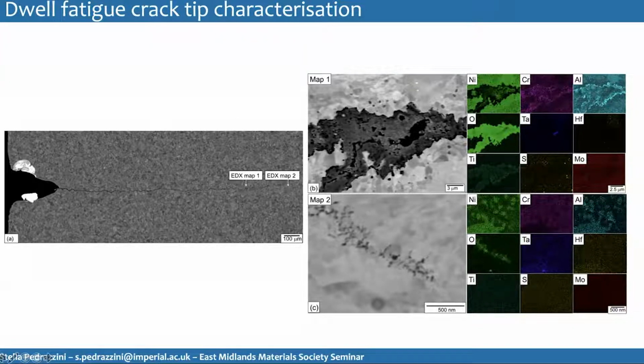At the very edge of it, what I got is alumina. Actually, there's no evidence of sulfides forming. So this looks like the crack initially propagates through a mechanism of formation of chromium titanium mixed sulfides that then oxidized as the crack goes ahead, and that's why we detect these chromium titanium oxides within the oxide in the crack. And then the sulfur is released and can go ahead and form other sulfides ahead of the crack tip and keep embrittling it. But at one point,